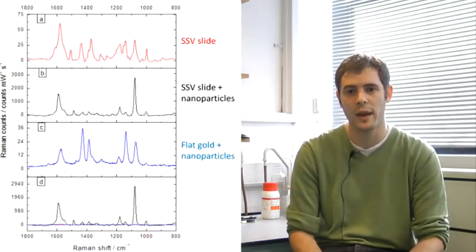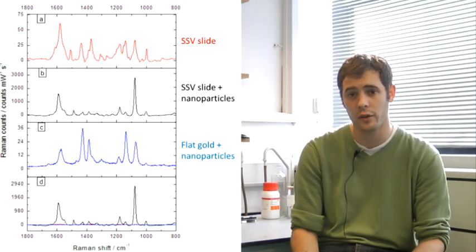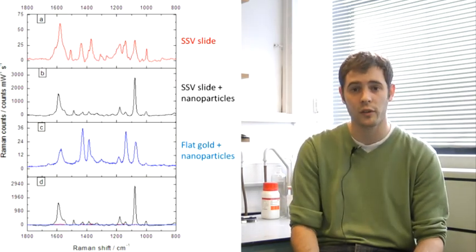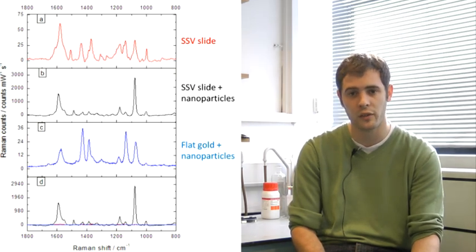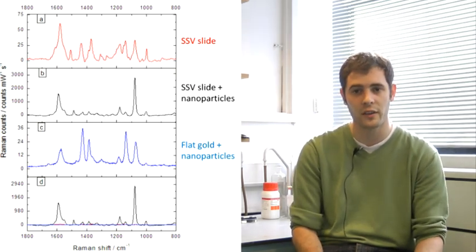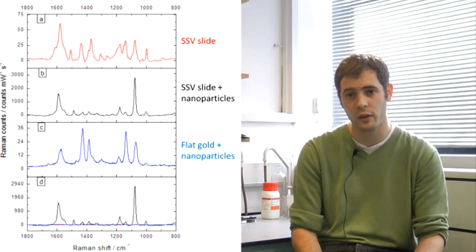The spectrum that we have is actually about a thousand times stronger than it was without the nanoparticle, which is a huge increase when you consider we've got a 10 to the 6 increase just by using the surface, so overall that's a kind of 10 to the 9, 10 to the 10 increase over just having the molecule by itself.